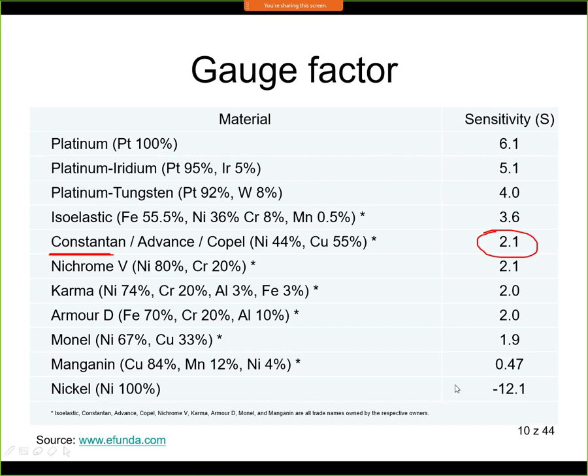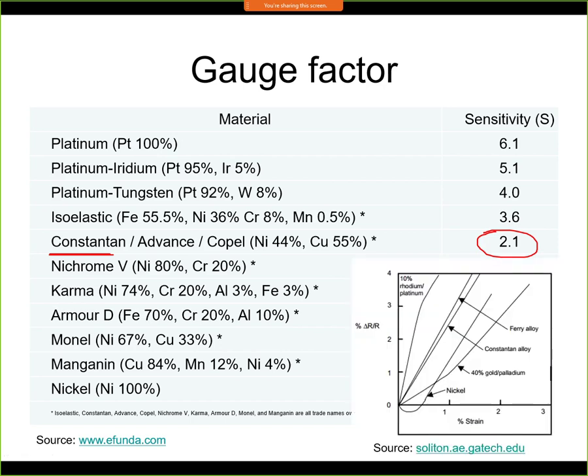From this table, we can see also that nickel would seem like a good material for strain gauges. The sensitivity is negative, but this is not a problem. It looks like 12. Okay, that would look very nice. But unfortunately, if we look at the dependence of the resistance versus strain, we'll find out that it's non-linear. So we can see on this chart that the negative sensitivity corresponds to the origin here. We can see the negative slope, so it is decreasing resistance when we increase the strain. And then we have an area where the sensitivity is very small or 0. And then in this area we have a positive sensitivity, and here we have a linear dependence. So nickel is not a good material by itself. We need an alloy of nickel and copper.